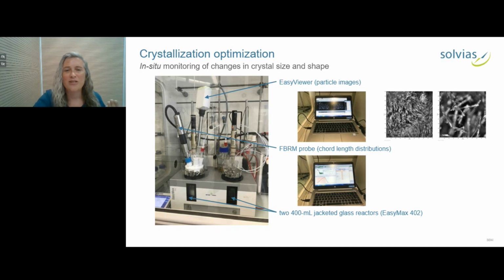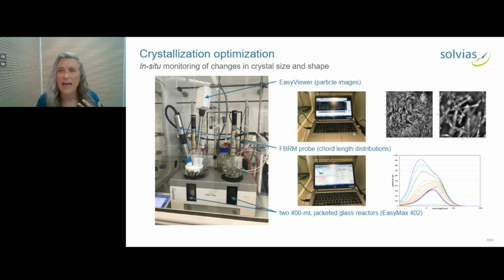So the distributions you get are not exactly the same as you would get from a laser diffraction particle size distribution. But what it does give you is a way then to follow your crystallization process. So if you have a distribution and during the process it's moving toward larger sizes, then you see you have growth. If you have a sudden appearance of fines, you have nucleation.